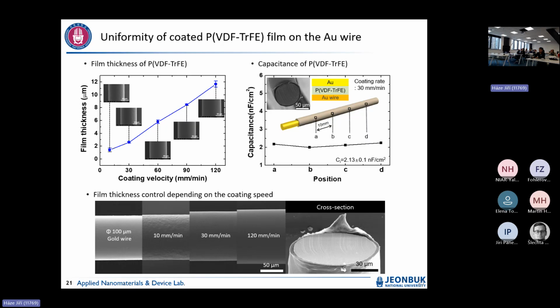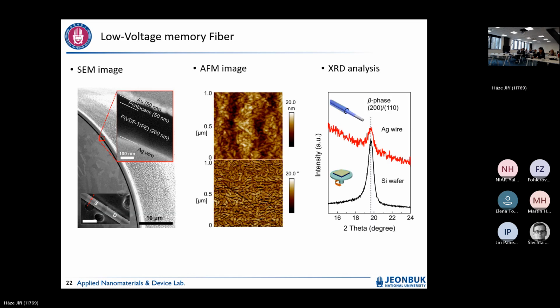So you can see here, when you cut very carefully, you can see the nice coating of the PVDF-TrFE layer on the wire. So this is the cross-section for right angle fabrication of the transistor. You can see the bottom is the silver wire here. Then PVDF-TrFE is around 260. Then pentacene is one of the p-type semiconductors.